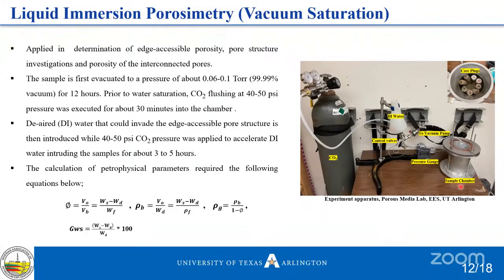I want to mention that this was done at the lab, free. The porous media lab was able to fabricate this locally. This can be made in Nigeria by any welder. It's a very simple thing. The job of the department or the industry or whoever is involved is to make sure that this can form a seal when you lock it. So this is put inside this place, and then I use these screws to tighten it. And we have this grease that we use on the top so that there won't be any air coming in or going out, so it's airtight.